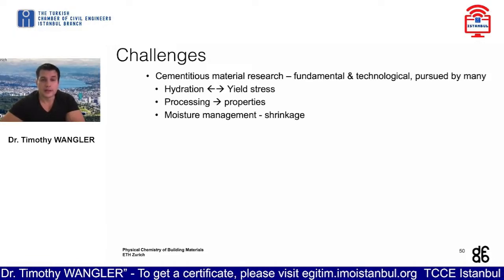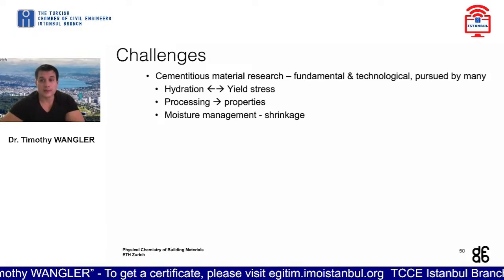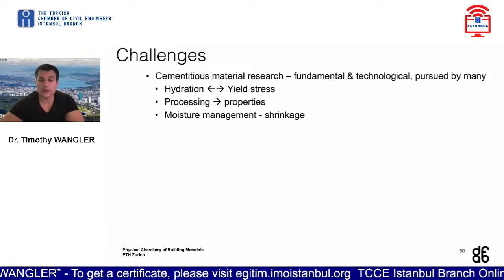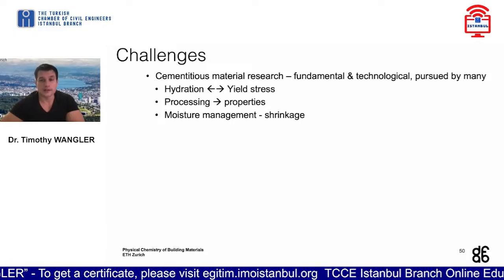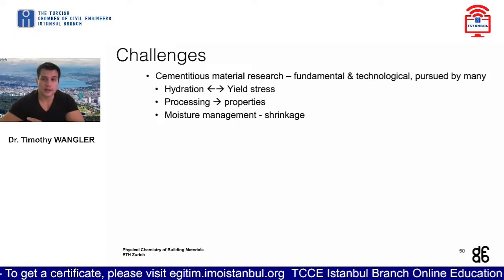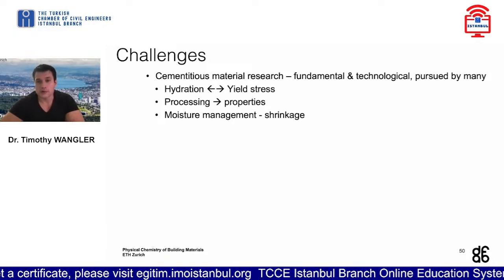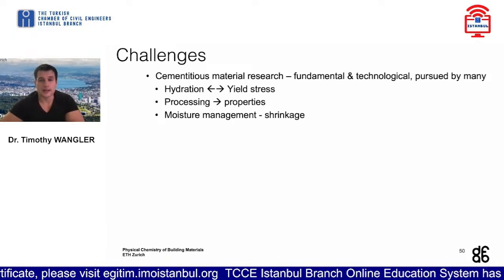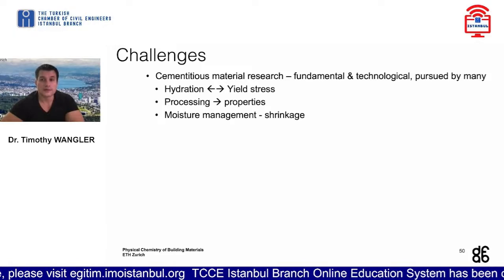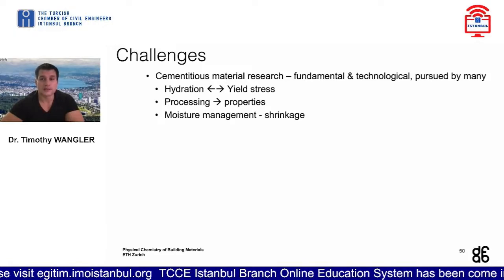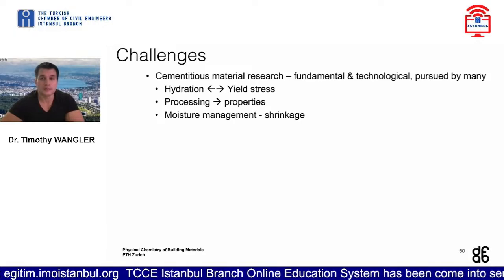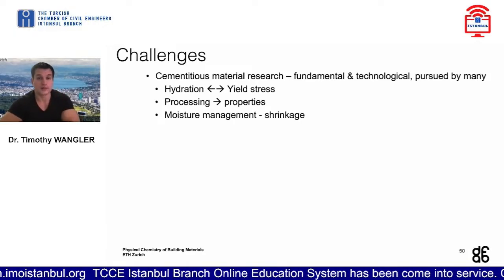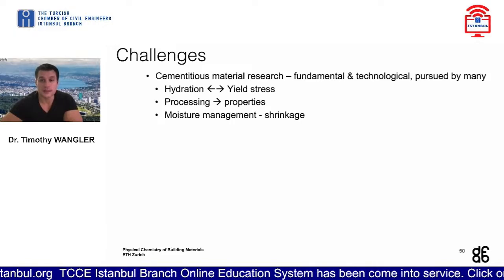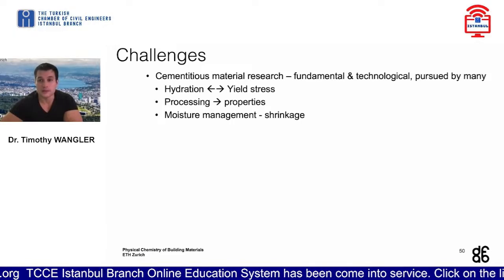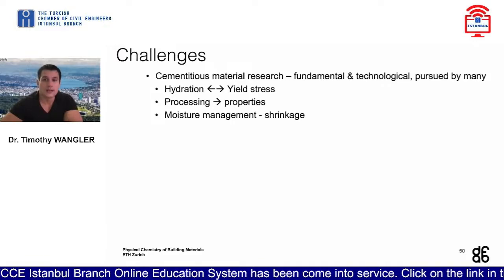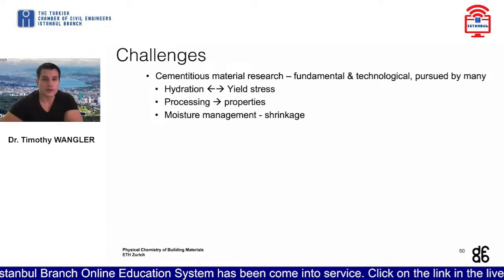One thing I didn't mention here, which is worth mentioning, is that if you remove the formwork from the construction of concrete, one of the functions of formwork was to serve as a skin for curing. And when you remove it, you suddenly have issues related to shrinkage and drying shrinkage. And so curing becomes another issue that needs to be addressed. And it's also a topic that's underway in many research institutions in how to manage the lack of a formwork.